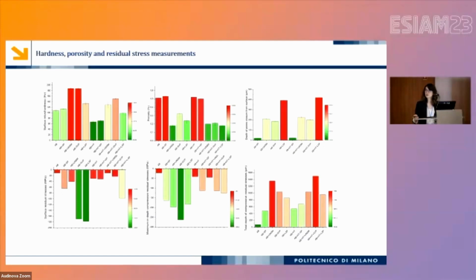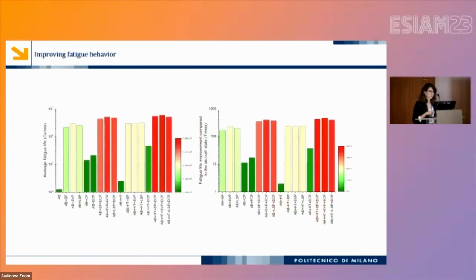And we are inducing compressive residual stresses with all these treatments. So again, to different extents in terms of surface residual stress, the depth of the layer that is affected by compressive residual stresses, and the maximum value of the residual stresses. On the other hand, the chemical and electrochemical treatments are not interfering with these parameters. So they are mainly reducing the surface roughness, but not inducing, obviously, any residual stresses or changing the micro-hardness.